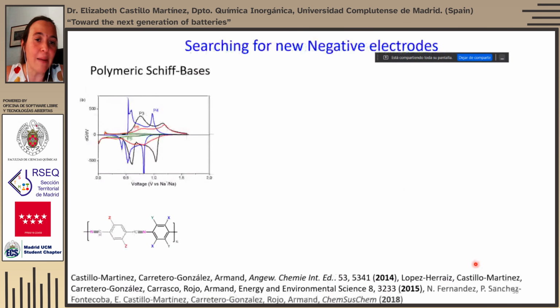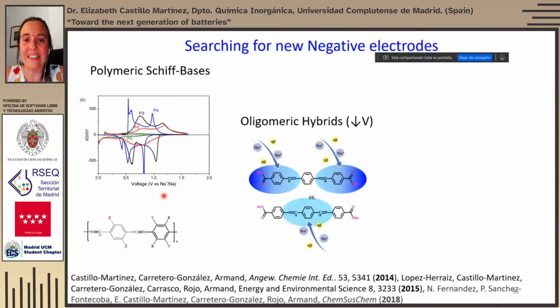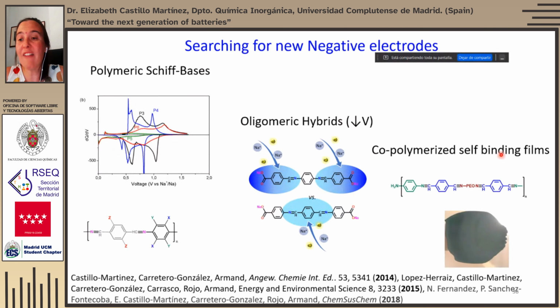And I'm going to show you an example of my own research here, where we prepare polymeric Schiff-bases and propose them as electrode materials. And actually, we saw that the two redox processes, which change in voltage with the change of substituents, do take place at voltages close to 1 V versus Na/Na+. And therefore, it's interesting as an anode material for sodium-ion batteries. We could also go to lower voltages if we hybridize these Schiff-base units with carboxylates, or we could even make a self-binding thin film by copolymerizing the Schiff-base functionality with polyethylene oxide units.